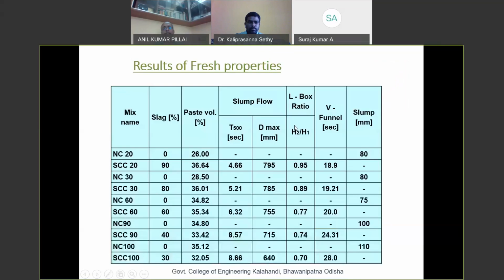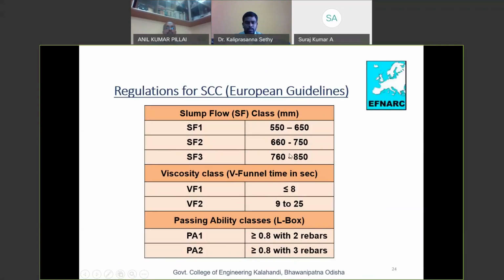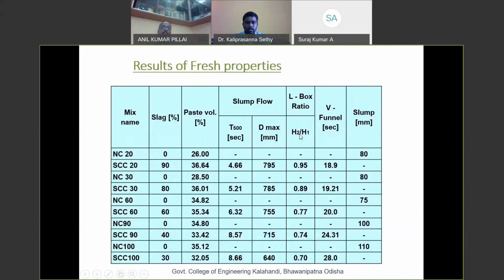Here are the fresh property results tabulated in this table. You can see the slag percent replacement, paste volume, the seconds which we have discussed, and this is the D max value. You can see 795, 785, 755. All the slump flow values are coming within this range, SF2 and SF3. And this is the L-box ratio H2 by H1: 0.95, 0.89.